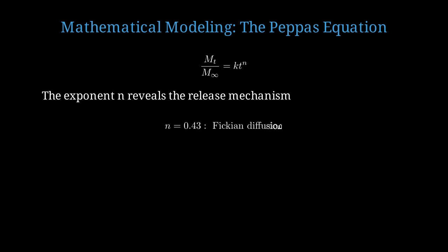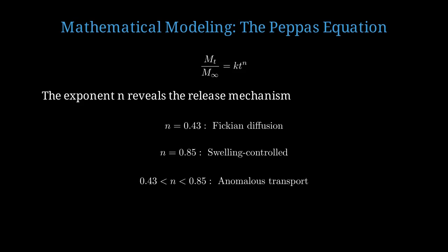For n equals 0.43, we have Fickian diffusion. The release rate decreases with time as the concentration gradient diminishes. For n equals 0.85, swelling controls release. The polymer network relaxation is the rate-limiting step. When n falls between these values, both diffusion and swelling contribute to the release mechanism. This is called anomalous transport.